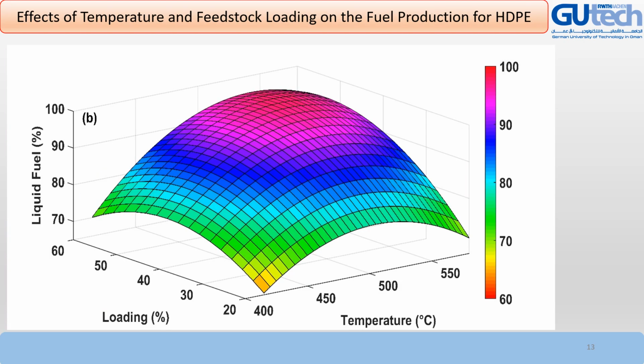This figure shows the effect of temperature and feedstock loading on the fuel production for HDPE. As you see, the same trend as temperature is shown for the loading. So by increasing the loading, the liquid fuel efficiency increases, reaches the maximum, and then decreases again. Maximum production is performed at 509 degrees Celsius.